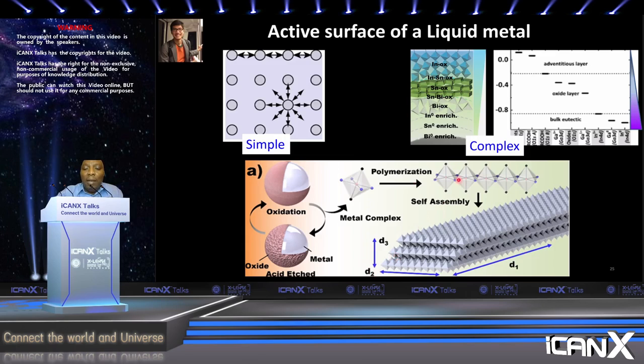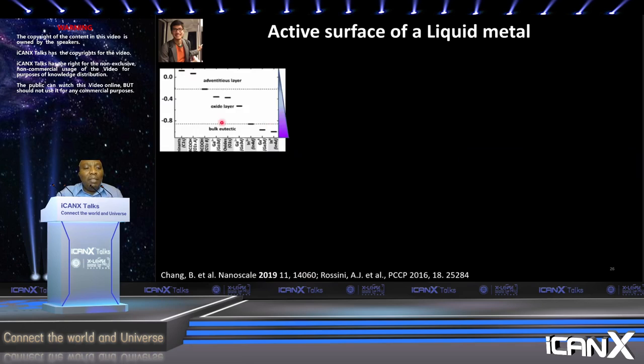So, for example, if I have a hydrogen bond on this plane and a van der Waals interaction on the other, then of course the hydrogen bonding components are going to grow faster than the methyl-methyl interaction components that I impose on the other side. And so we went back to EGaIn and we said we start with a binary metal because it's simple.